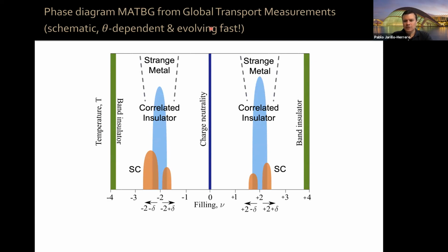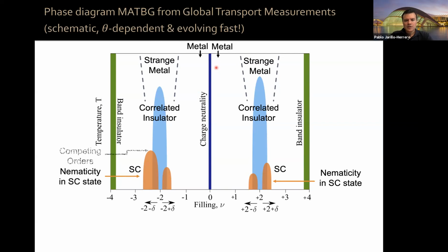First thing is we saw a region of linear in temperature resistivity behavior, very reminiscent of the strange metal behavior in correlated systems, when that happens around the correlated insulator regions, okay? Whereas if you go to near charge neutrality, the system just exhibits the typical metallic behavior, let's say with a quadratic temperature dependence of the resistance. We also saw that the superconducting state exhibits nematicity, okay? It exhibits an anisotropy, and I'm going to talk more about this today.